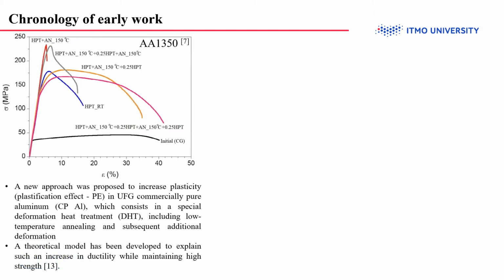Recently, it was found that a special additional deformation heat treatment, or just DHT, consisting of low-temperature annealing plus additional small high pressure torsion deformation, provides a significant increase in ductility of high pressure torsion processed aluminium while maintaining a high level of strength. Deformation-induced increase of ductility is not typical for coarse-grained metals. A theoretical model was proposed to explain this plastification effect, or just PE, in UFG aluminium.